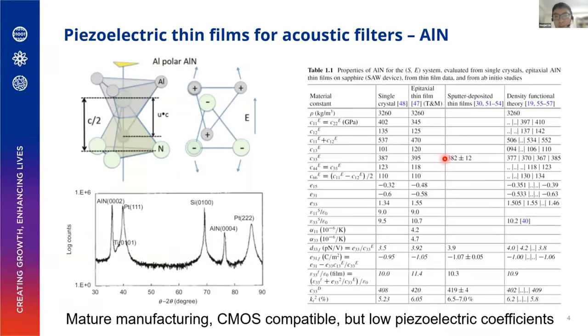Okay. So as material scientists, we always look at what the material is, and what we can do in the material improvement. So if you look at these two classic materials for this application of acoustic filters, the first one is aluminum nitride. So this is the polar structure of aluminum and nitrogen. So this is a simple crystal structure, and this is just piezoelectric. It's not a ferroelectric, so that means the polarization is not switchable by electric field. So this actually leads to good stability of the device, and it's not sensitive to the temperature or other stimuli.